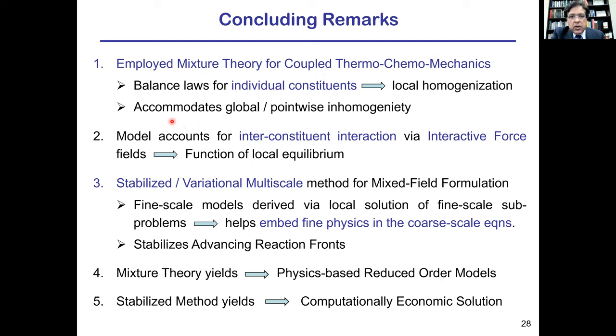The model also accommodates pointwise inhomogeneity in the material, while it accounts for the inter-constituent interaction via interactive force fields, which appear because of the local force balance in the evolution of the material. As the material is being formed, mass is being exchanged between the constituents. That gives rise to mass exchange-based interactive effects between the constituents. If the fluid constituent flows relative to the solid, then a viscous drag coefficient gets induced on the solid and vice versa on the fluid.